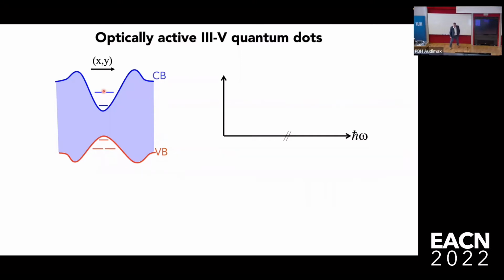But nevertheless, you can imagine that each one of these orbitals can be populated by two carriers, two electrons, one of either spin. So if we excite this system and we create lots of electrons in the conduction band, and by definition then lots of holes in the valence band, what you end up with is a series of many particle states. So here you see 4 quasi-particles, which are holes, 4 electrons in the conduction band, so 8 particles in total. And these particles are all trapped inside the quantum dot.